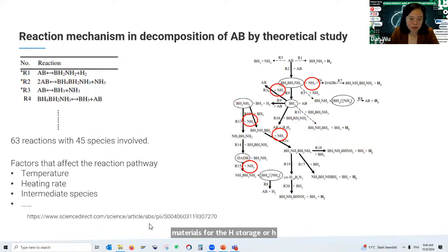And this is a publication which is done by a US research group. And they have actually started, first of all, with quantum mechanical calculation. And although the ammonia borane is a very simple material, let's say, if you start the reaction, it actually ends up with 63 reactions with 45 species involved in the whole process. And this is, of course, not wanted in real industry use because you want to find out what is the best way or most effective way for the reaction path. Yeah. And in this case, the first theoretical studies bring them to the most promising way as shown here.